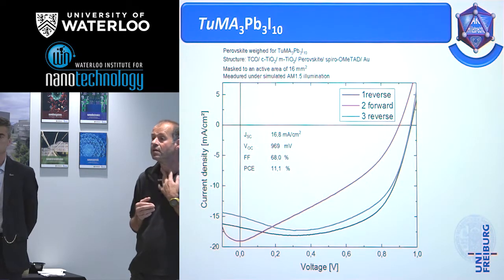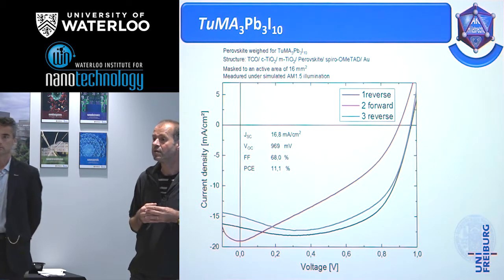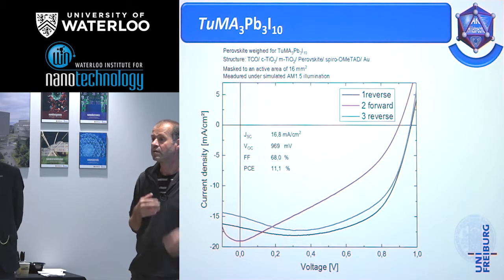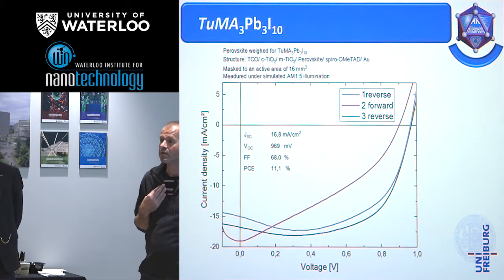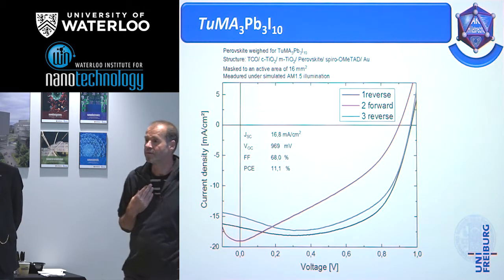I understand that the voltage hysteresis from the halide migration is a real problem. Joachim Meyer produced a nice paper on that a few years ago, seemingly showing that there was actual migration of the halides. And is that suppressed by the thiocyanate?